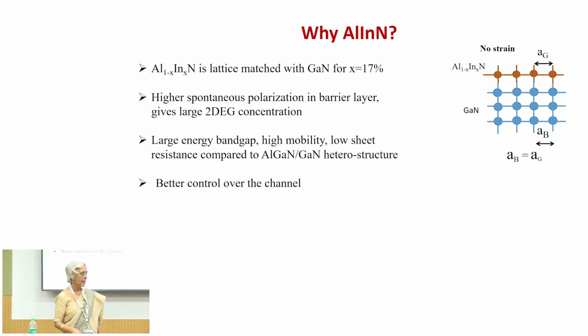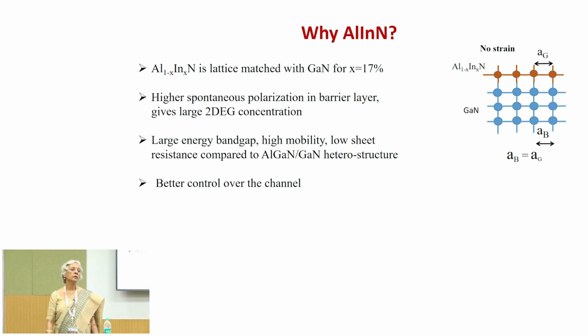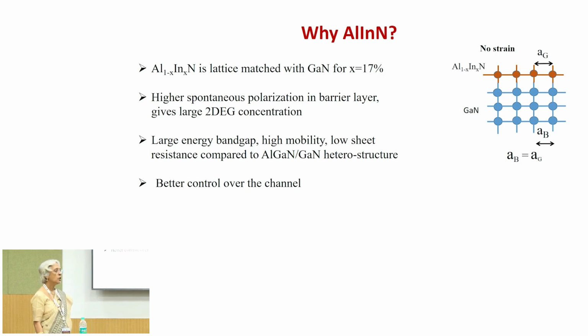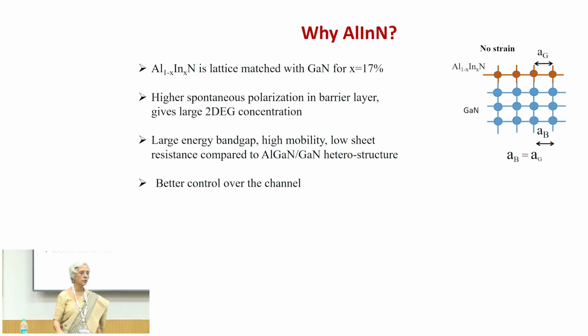Now, because it is lattice matched, obviously the strain dependent polarization, which we call the piezoelectric polarization, will be absent in the aluminum indium nitride layer. However, even though the piezo polarization is absent, we have a much higher spontaneous polarization in the barrier layer, and therefore, the two-dimensional electron gas density is much higher in the aluminum indium nitride gallium nitride system compared to the aluminum gallium nitride system.